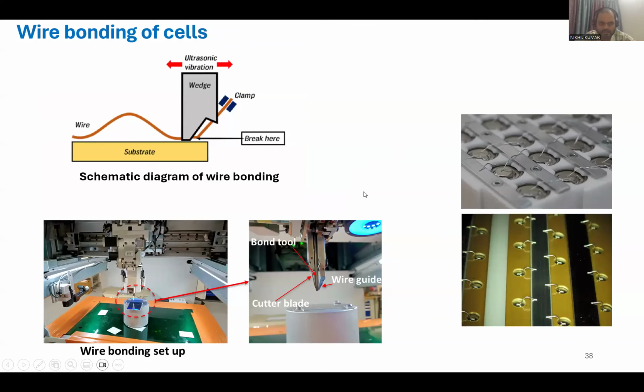Yeah, this is another welding process. This is wire bonding. As I mentioned, vibration energy is used for welding this wire to the substrate. This is the connecting wire, and for joining this wire we have used vibrational energy. The ultrasound frequency is about 60 to 80 kilohertz, with very small amplitude, because this is a very soft material, 99.99% pure aluminum wire. So we have only used a very small amplitude of the ultrasound.